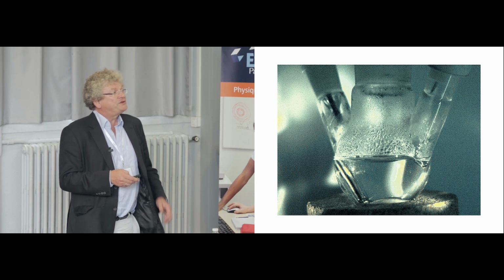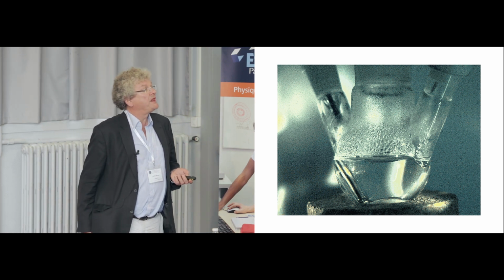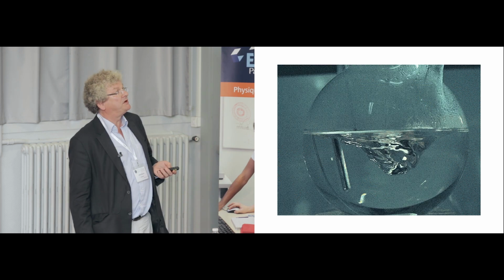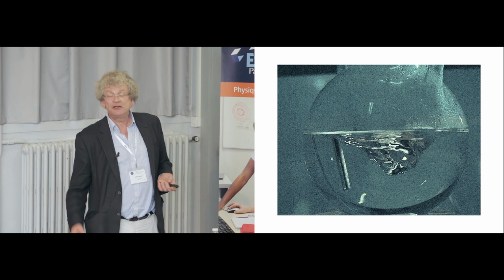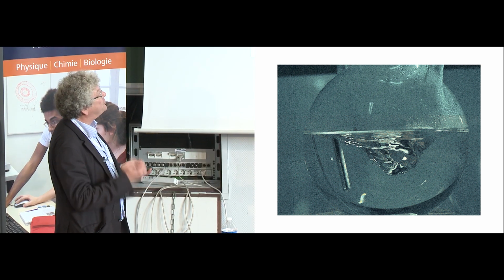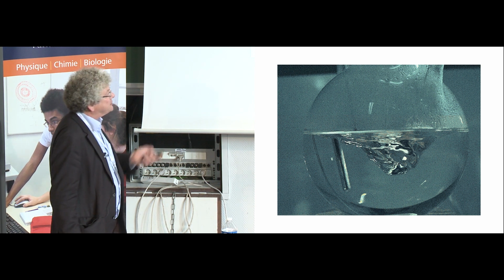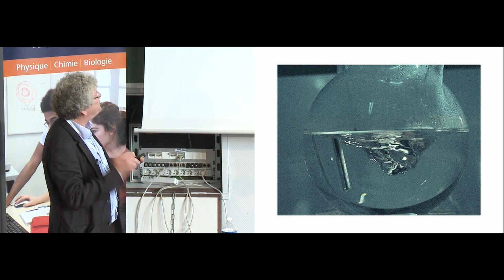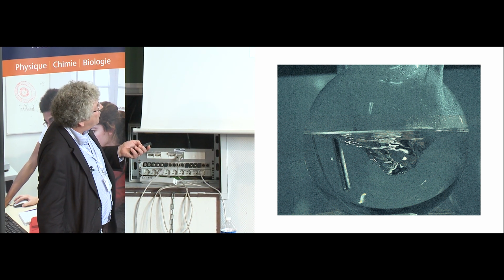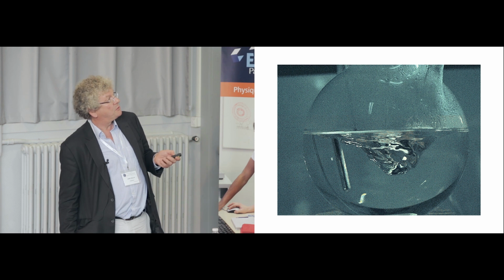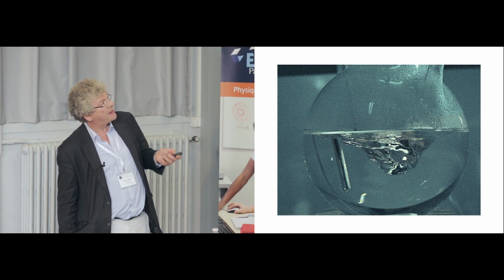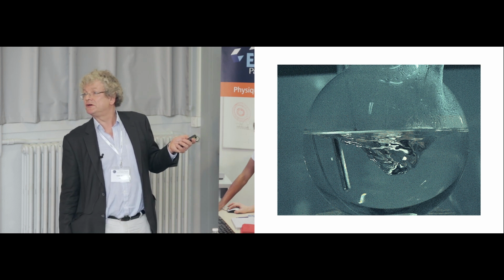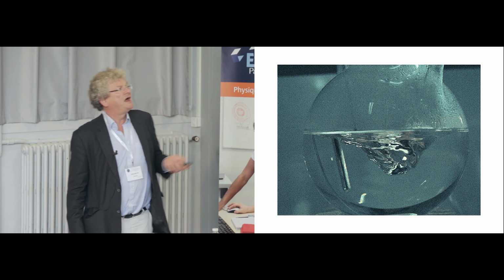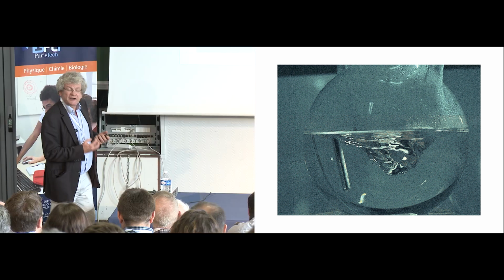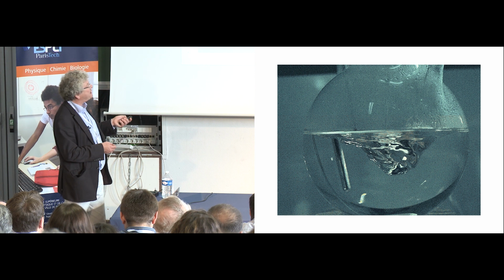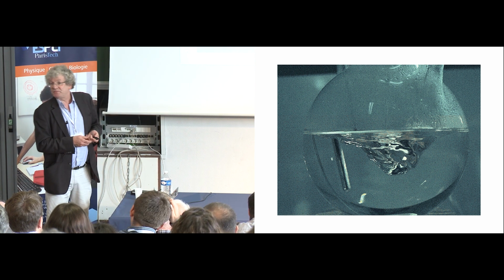And if you want to use them for some applications, you need more. And this is the same with a scale-up in a 2-liter flask. And the same solution, we inject in the same way, but it's a larger amount, can't do it so quickly. And the same person, so he really tries to inject as fast as possible. But what you will see here, it's getting black. Here it's getting black. So that means particles are formed. Here no particle is formed. So it's really now a matter of how you mix and how you start, how you separate that nucleation from growth. And this reaction will never lead to monodispersed particles.